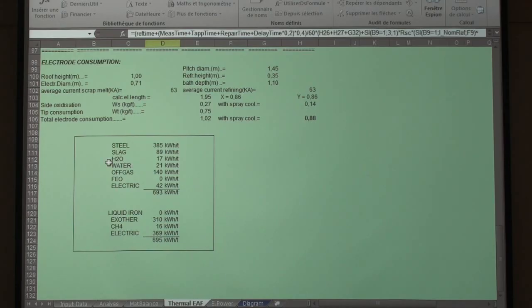This is the water-cooled panels here. Off-gas is in a range of 120 to 150 kilowatt hours per ton, depending on how much fossil energy you put, because fossil energy will create a lot of CO. So if you have a lot of CO, you increase the off-gas energy. FeO, this is eventually the reduction energy for the DRI, so it depends on the DRI. And this is the ohm losses. Electric is ohm losses. You remember the resistance in short circuit, times half current, square current, and so on.